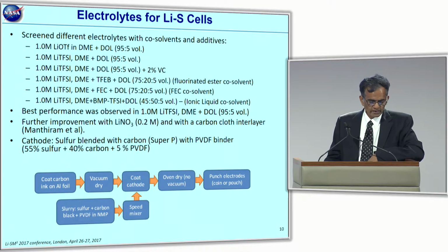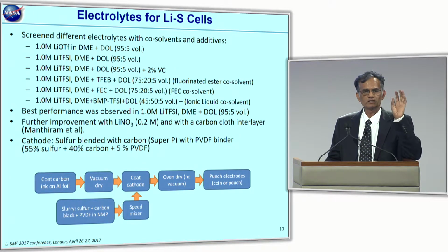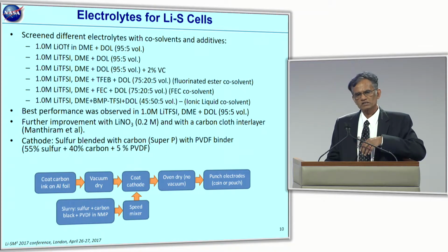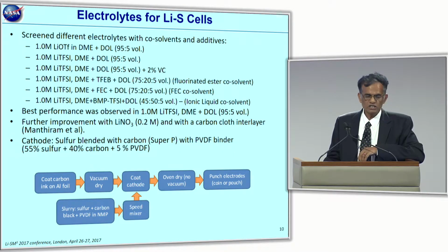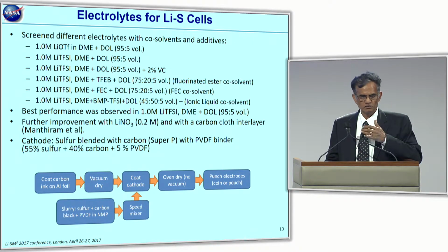And what we did here is, this is by no means an exhaustive survey of the electrolyte, but we quickly screened various combinations to see what is the best one. Our focus has been to develop a dense, stable cathode. However, we looked at different electrolyte options here. We mainly stuck to this DME-DOL blend, and we looked at triflate as an option, imide salt, and also some of the additives like VC and FEC. These are the standard additives that we tried, and we have seen some beneficial effect in lithium-ion cells.